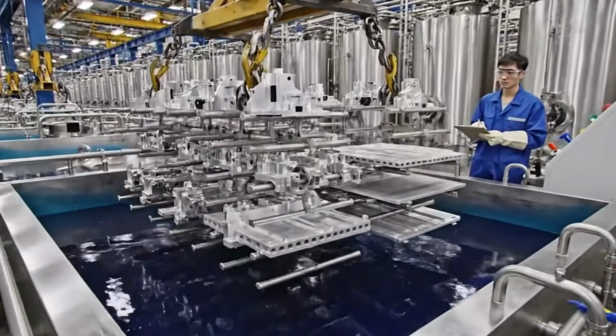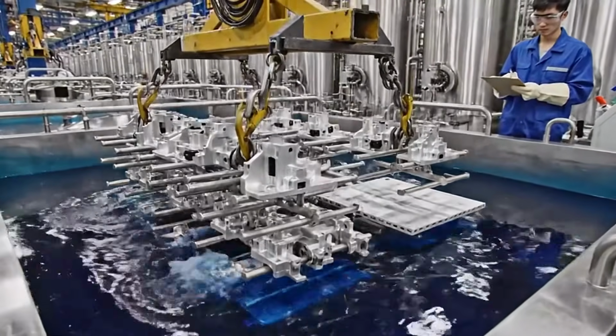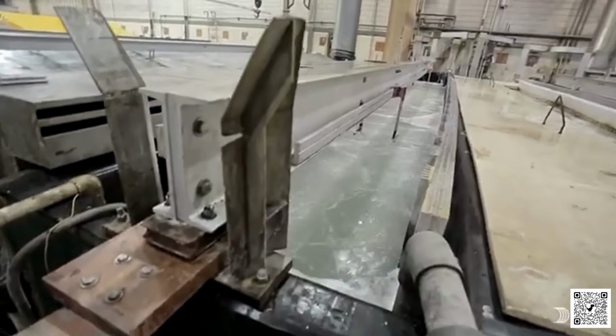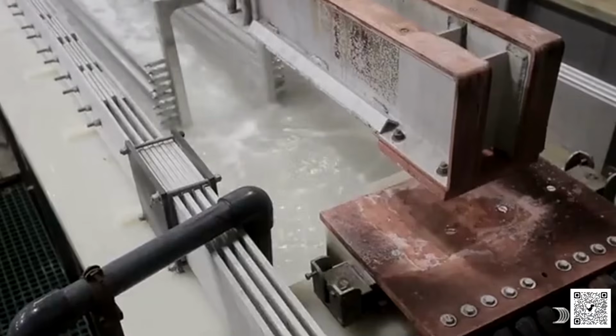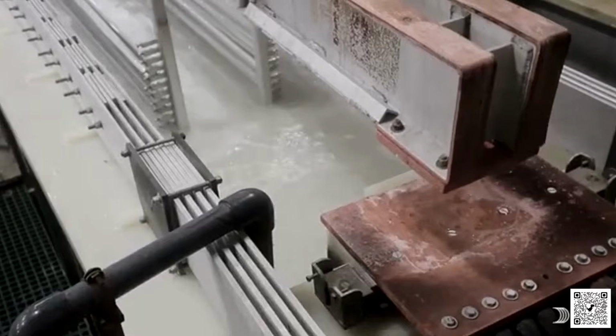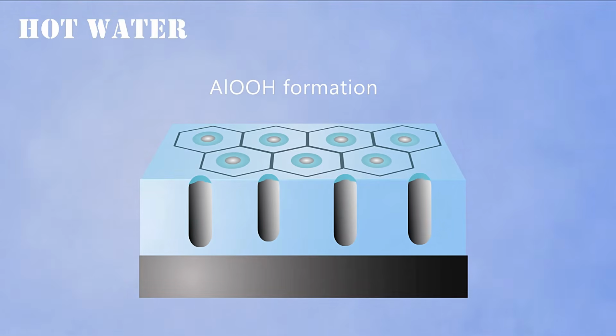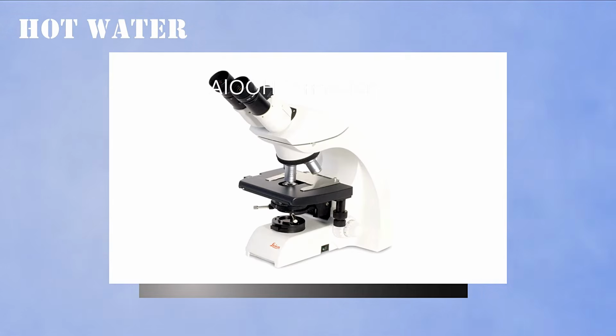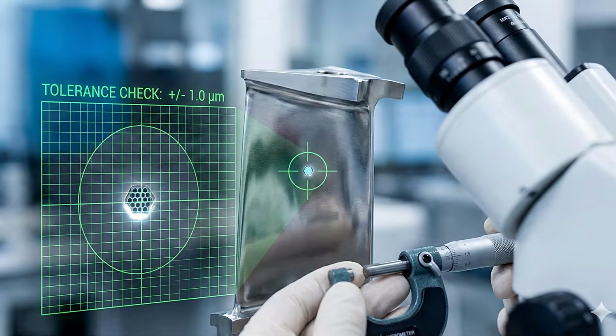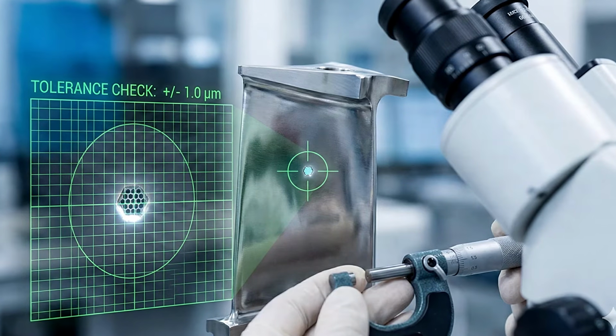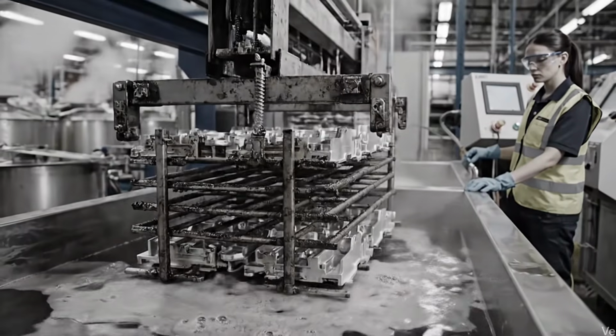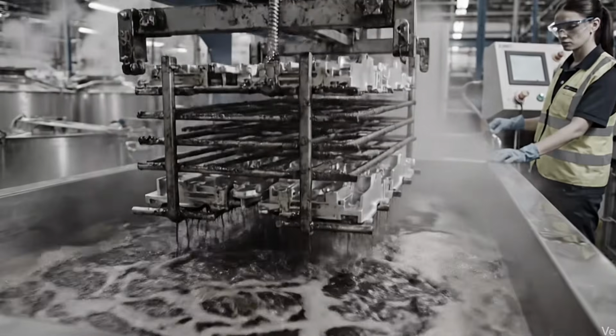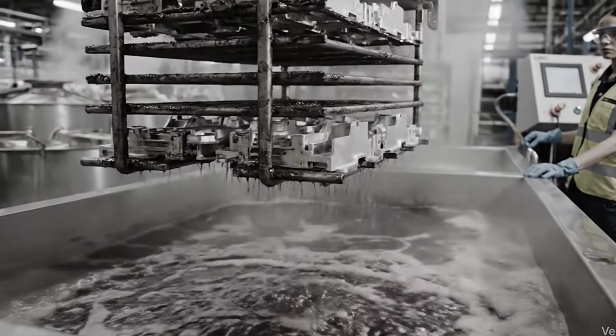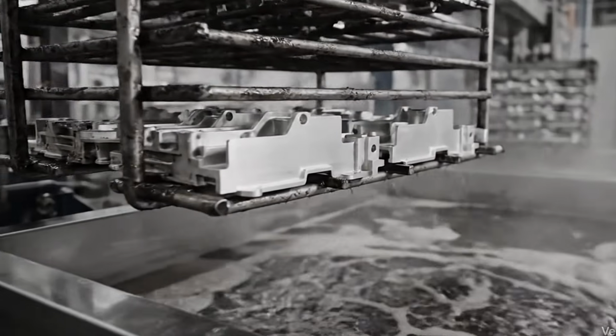After anodizing, the pores are either dyed or left clear. Finally, parts are sealed in hot water or nickel acetate, hydrating the alumina so the pores swell shut like closing millions of microscopic umbrellas. Thickness is checked with eddy current probes or optical microscopes. Aerospace specs can be tight to within a micron. All of this happens continuously, 24/7, in factories coating millions of square meters of aluminum per year.